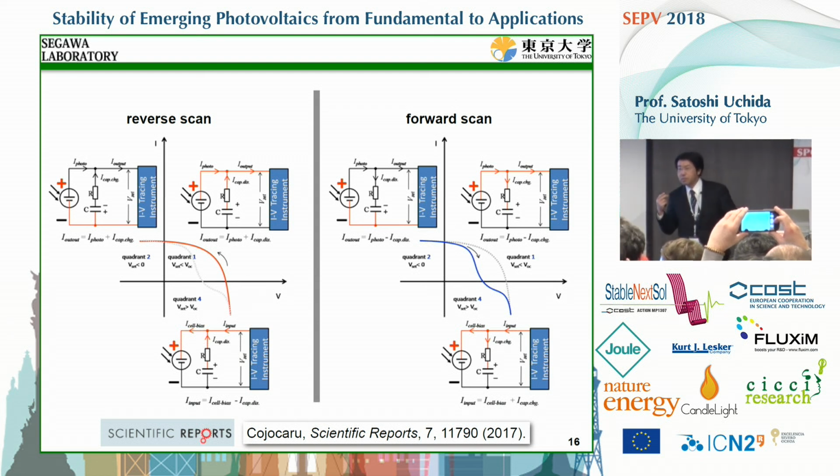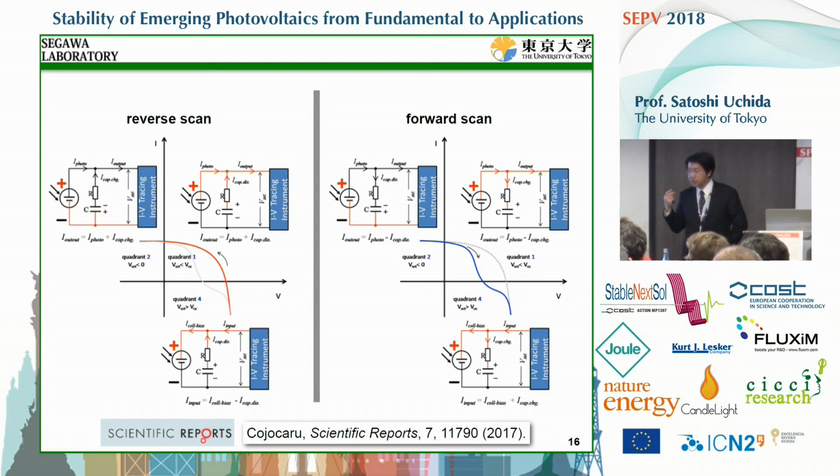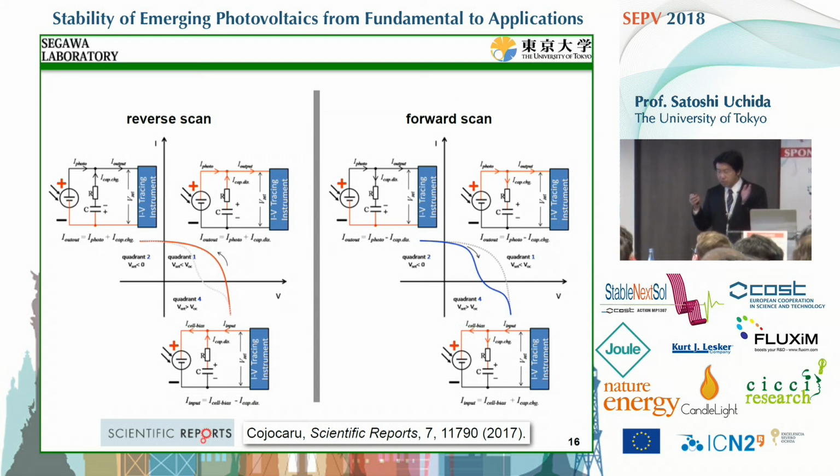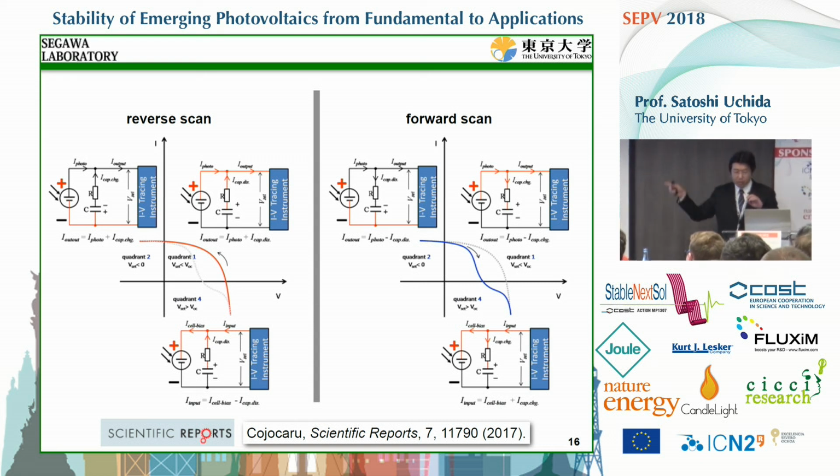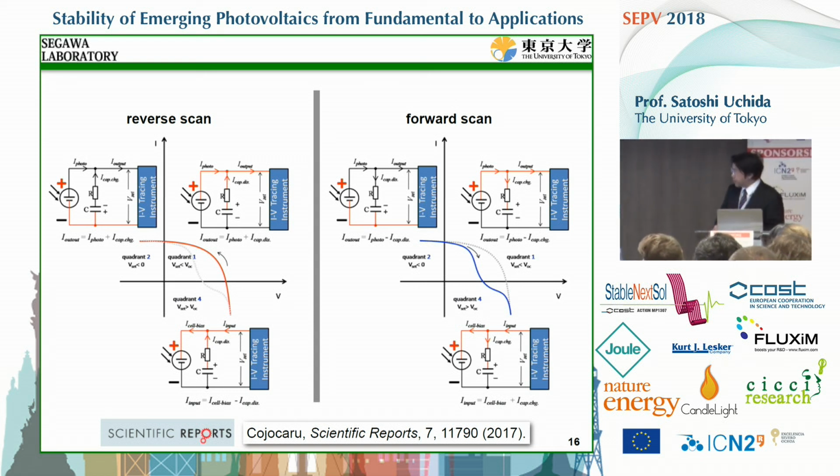Now you can understand, because at the high intensity condition, which means high current conditions, such charge-discharge current doesn't affect so much. But if you decrease the intensity, the capacitance doesn't change, and finally at a certain point it affects. The fake current may overlap, and then it's a kind of definition issue.